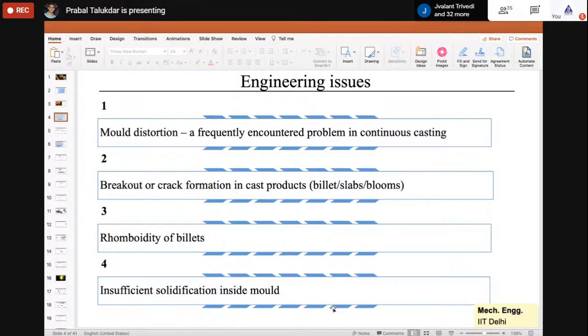Mold is the channel through which the liquid metal comes, and the liquid metal converts to a solidified shell, that is basically the billet. So there can be a problem in both, in the mold, and in the billet, or slab, or blooms also. Rhomboidity of the billets is another problem. It is not cracked, and there is no breakout, but the shape of the billets changes because of the thermal stresses it encounters. That is another problem which one has to look into.